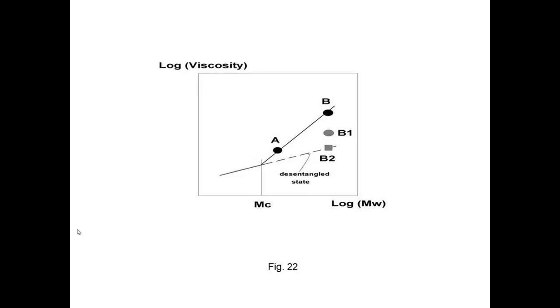The log viscosity versus log of molecular weight is a classical presentation of the concept of entanglement. The entanglement is seen here as the break in the curve at a critical molecular weight called M sub c, from which the slope of the log of Newtonian viscosity versus molecular weight passes from 1 to 3.4. There is a large increase of the effective molecular weight beyond the molecular weight for entanglement, or the critical molecular weight.